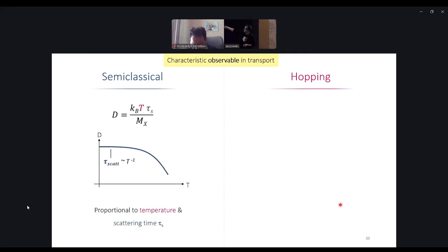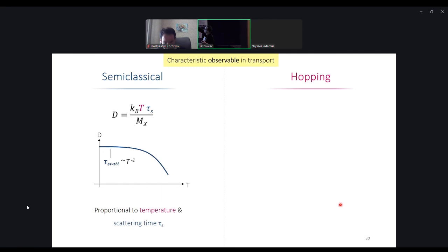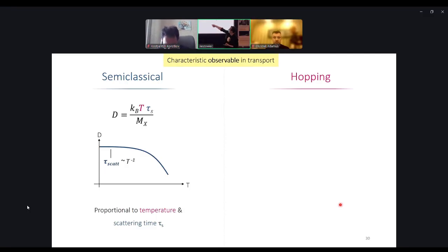On the left side, you have something that is typically expected for semi-classical propagation. Initially, you should not see any change in diffusivity as a function of temperature because, as you see, kBT on the top, the thermal energy drives the diffusion. So the diffusivity increases linearly with temperature, but if the scattering time is 1/T, then these two quantities cancel each other out, so you have something constant, and then at some point the scattering wins over, so it's basically something like a metallic behavior.